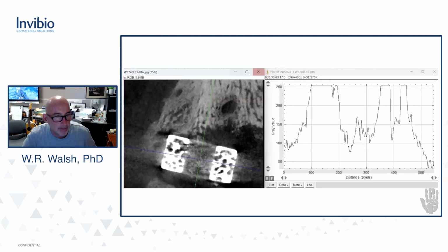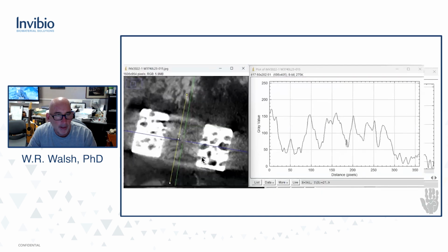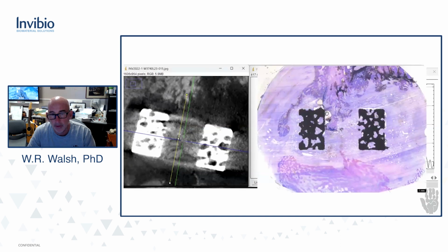This is that case that was infected. And what we did in this was we put a profile line in ImageJ just to get a grayscale analysis. You can see when the profile line hits the metal, it just peaks out at 255. But it's showing me some gray material in there. And this is when we passed the profile line of that same device down through the aperture. And again, this looks like there's some gray value in there, or is it scatter? And it looks like there's something in the walls, but is it just scatter? And it actually is just scatter of the artifact from the CT scan of the metal.